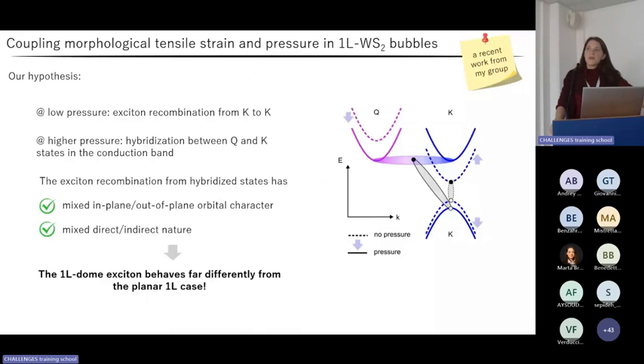To explain this anomalous behavior, our idea is that under the application of pressure, the variation in the complex strain gradients at work in the monolayer dome determines an anomalous evolution of the electronic band structure of the system. In particular, a hypothesis is that the Q and K minimum in the conduction band may hybridize, giving rise to an exciton band at high pressure with mixed direct-indirect nature and in-plane/out-of-plane orbital character.